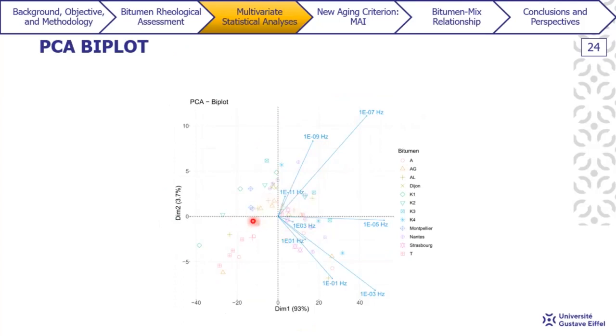So now, in addition to having all these individuals, that is, each individual is a bitumen that was located on this PCA biplot, we also have these zeros, which represent the initial values. And the longer the projection of this arrow on a given PC, the greater its influence. So the longest arrows that we have are these three, which correspond to 10 to the power of minus 3 hertz, 10 to the power of minus 5 hertz, and 10 to the power of minus 7 hertz. When we do the projection of this, we can see that both 10 to the power of minus 3 and 10 to the power of minus 7 have significant influence on both PC1 and PC2.